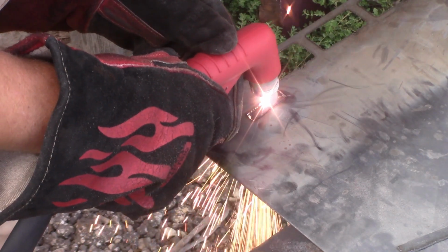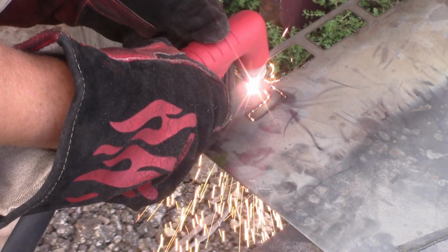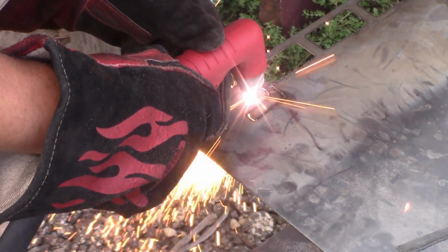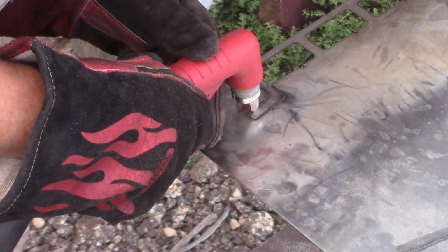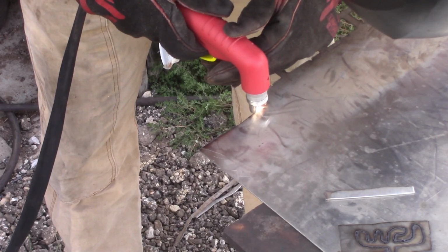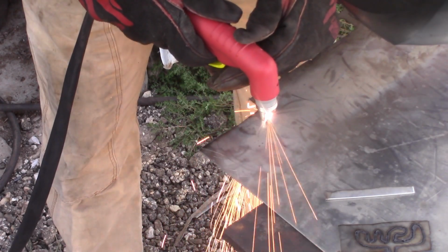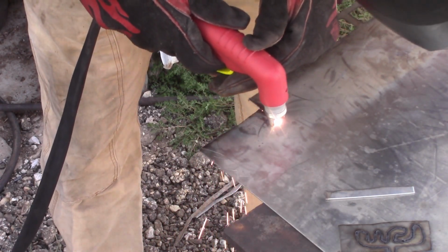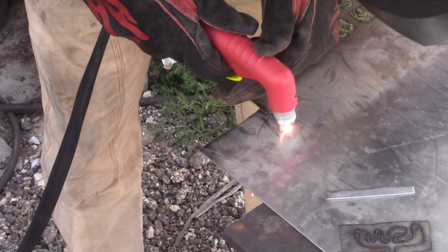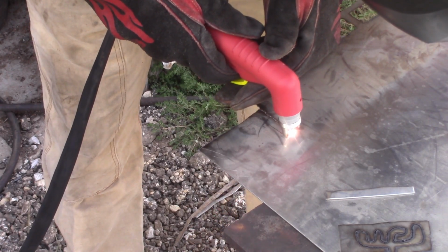We started these cuts at 20 amps and it cut for about 17 seconds before tripping the breaker. After I reset it, it tripped again after about 22 seconds. Even after lowering it down to 15 amps, it still tripped the breaker, so unfortunately we weren't able to test it all the way up to 35 amps using the 110 volt pigtail.